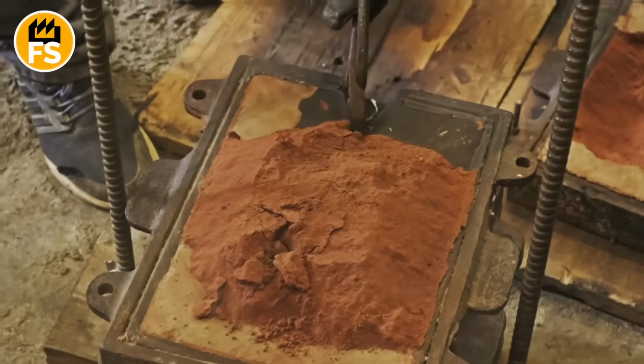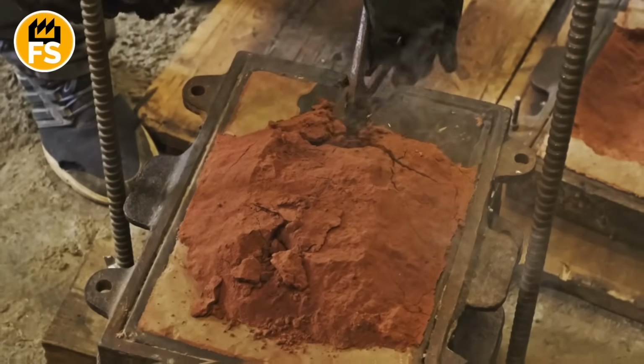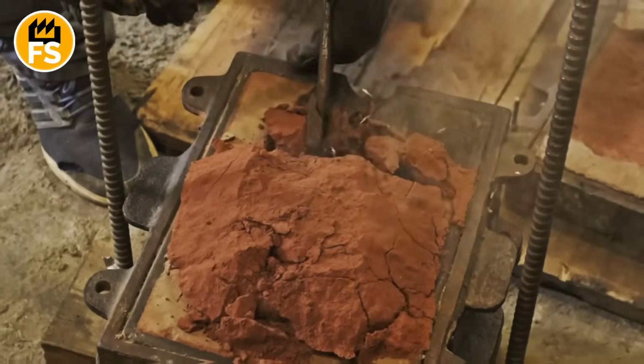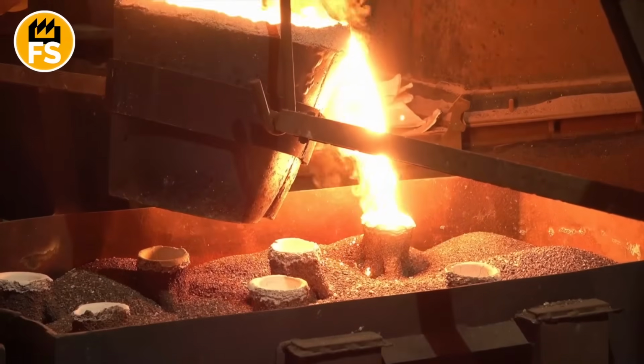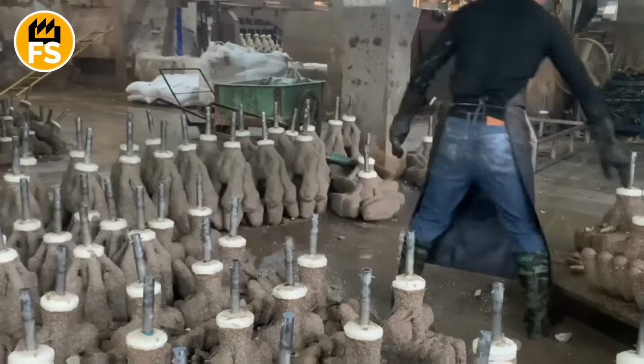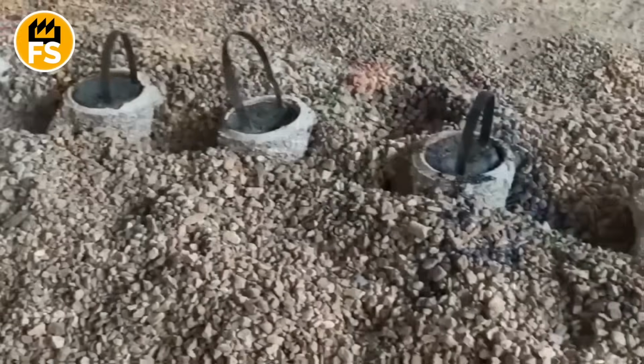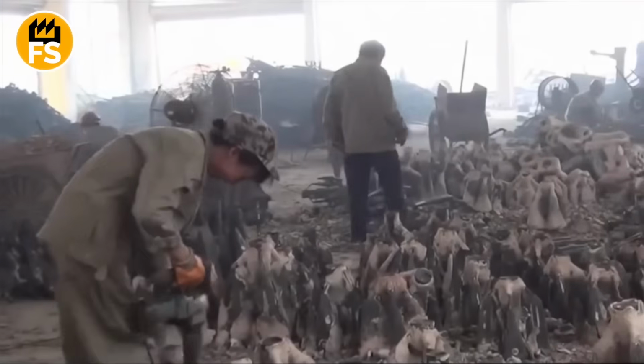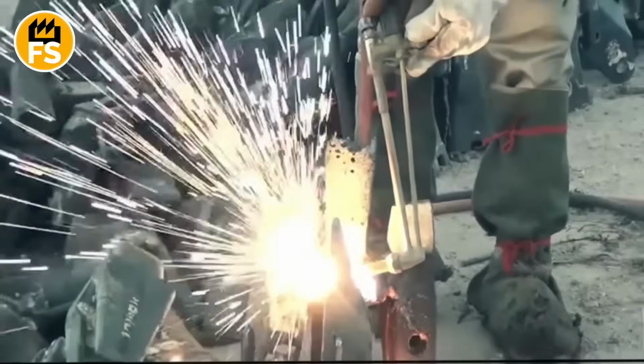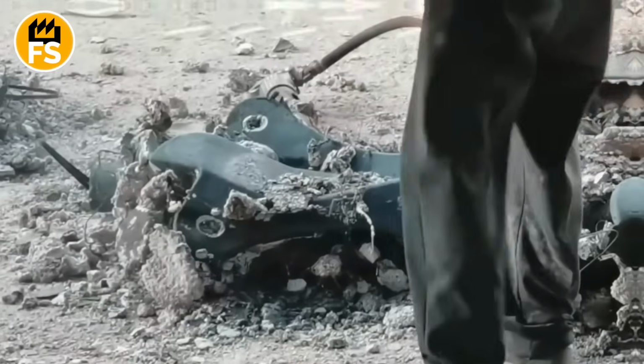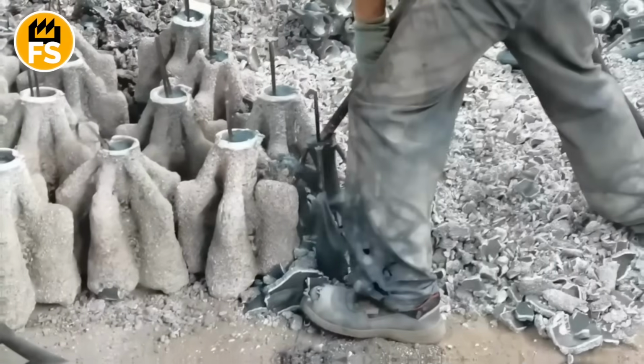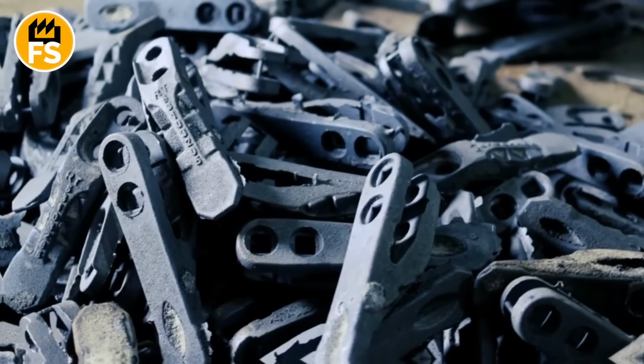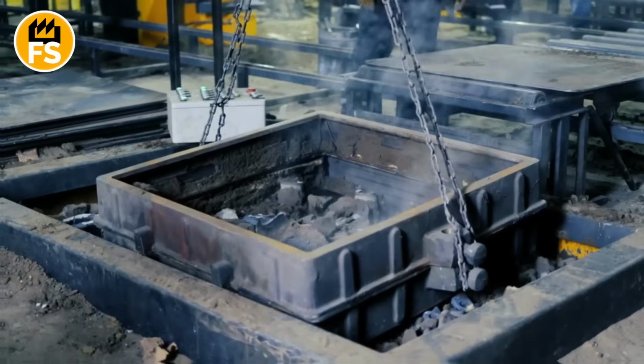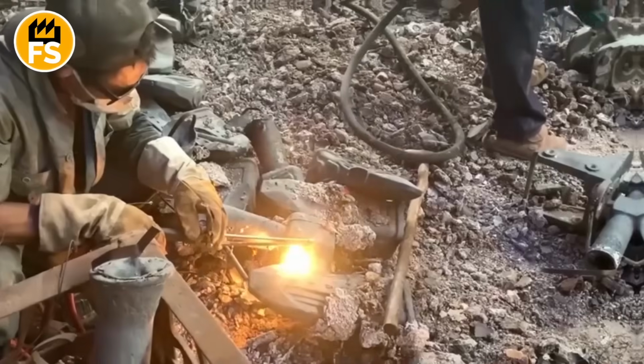The molten metal pours fast, but carefully. Air bubbles can ruin the entire part. After pouring, free cooling begins. This is critically important. The molds cool for 8 to 12 hours down to room temperature. Once everything's cooled, they break the ceramic shell. This is done with special hammers or sandblasting machines. And there they are, cast teeth, still gray, with ceramic remnants. But this is only halfway. The real magic starts now.